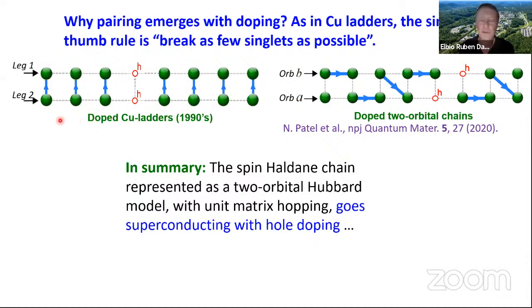It turns out that a good representation of the undoped ladder is to have a spin singlet along the rungs. Just a spin singlet here, the next rung, a spin singlet, and so on. These are true legs, no longer orbitals. So they are happily forming a spin singlet. If you bring one hole, you break one of the spin singlets. You pay energy. So naturally, if you have two holes, and if you want to break as few singlets as possible, then you just pair them. You place them in the same rung.